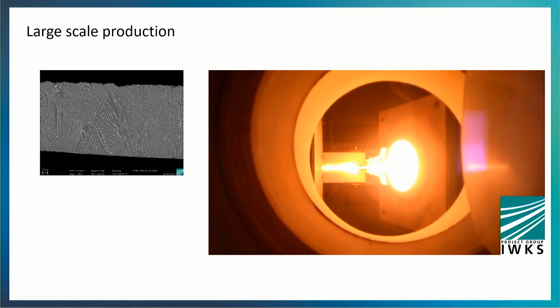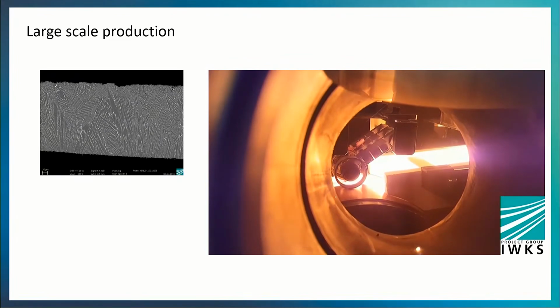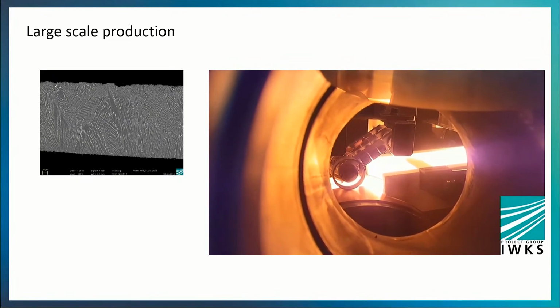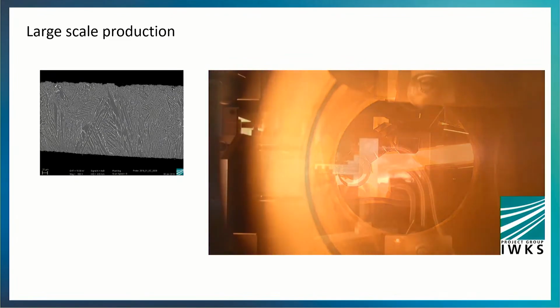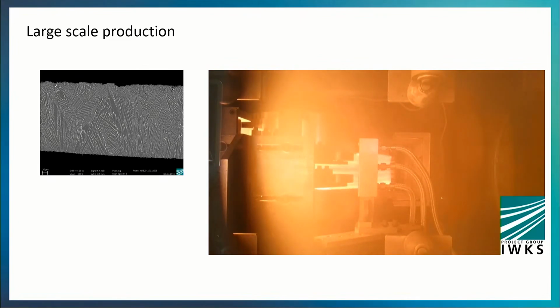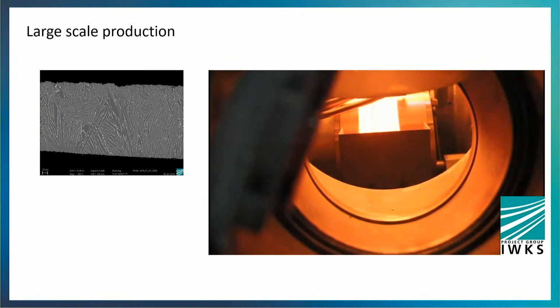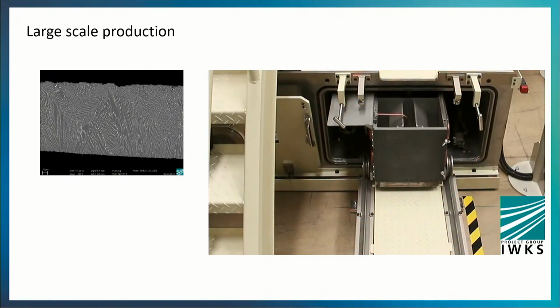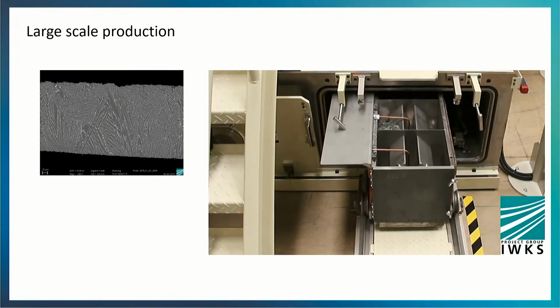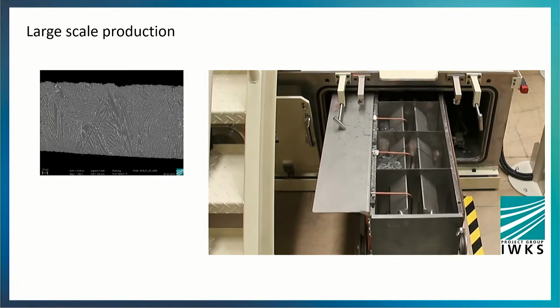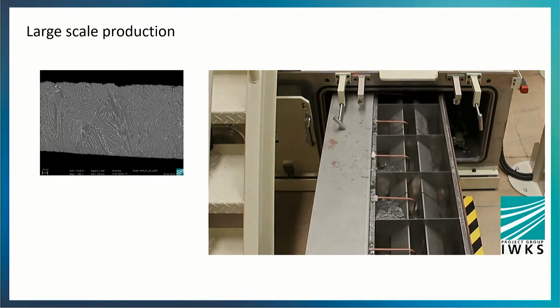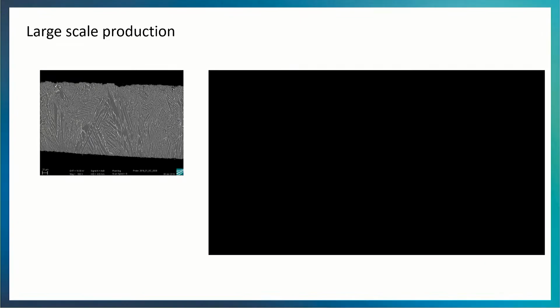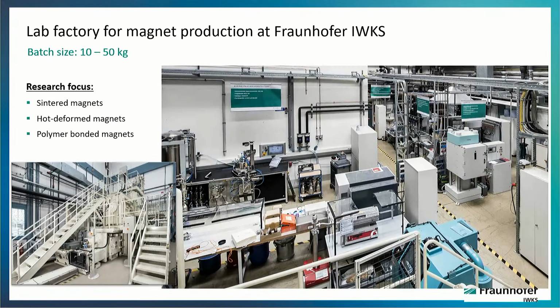Then we want to produce recycled magnets on a large scale, and this is done by melting the alloy, and the melt is dropped on a water-cooled copper wheel, as you can see here, and this produces a certain microstructure. We are producing large amounts of these flakes of recycled magnets.